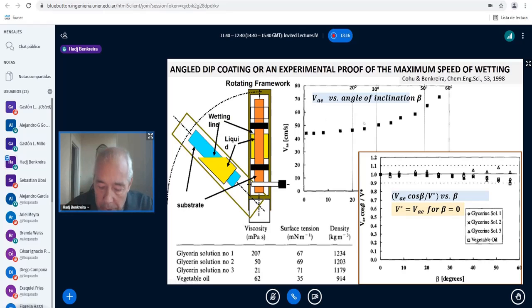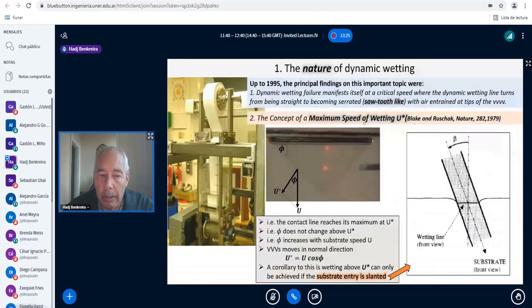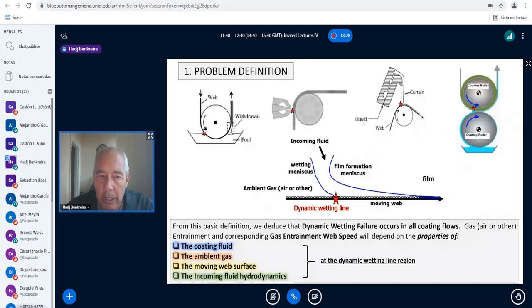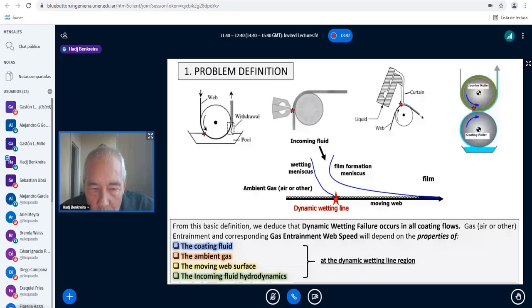And you may think that this operation is not feasible, but if you look, for example, at curtain coating or slot coating, all it means is turning your slot coater at a certain angle. By increasing the angle slightly, you can increase the production rate. Of course, you do not have to increase it by a large angle. You might want to increase it, say, by 10% or 20%, so you'll have to tilt it only very slightly. Okay, so that is finding number 1, which is very important.